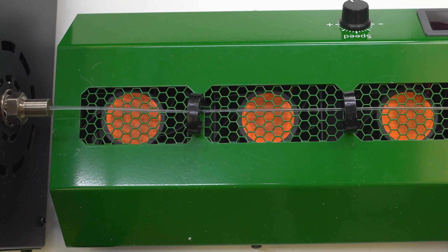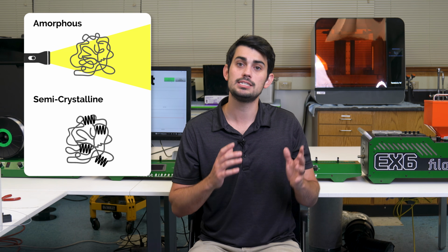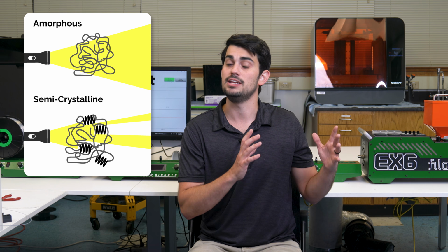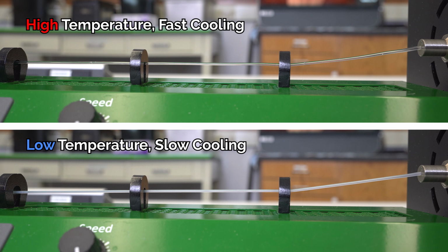Also, if you don't use any colorants, as I've elected to, you can create transparent filament given the correct extrusion temperatures. I had mentioned previously that PETG has low crystallinity. Generally, crystalline structures within a plastic object obstruct light due to their density. So if you can decrease or eliminate the formation of crystal structures when the material is cooling, then you can make it more transparent. The best way to do this is to cool the plastic quickly. This concept is, in many ways, analogous to quenching a metal. So extruding PETG at a high temperature and then cooling it quickly will create a transparent filament, but extruding it at a low temperature and cooling it slowly will result in a more opaque material.